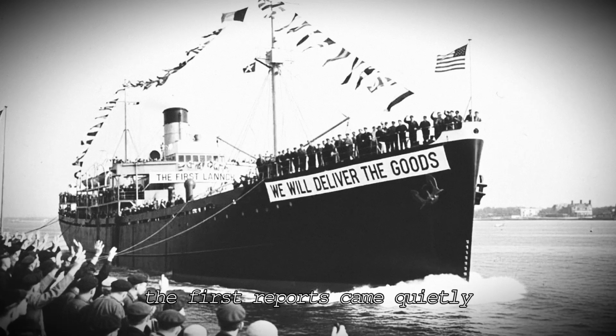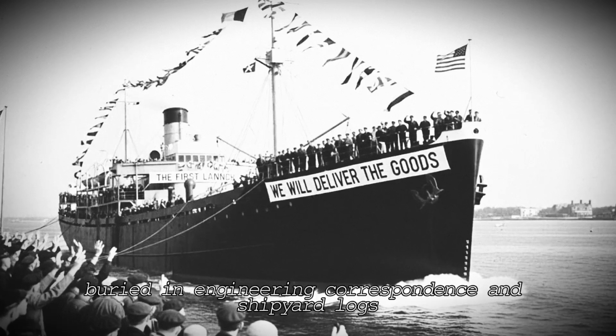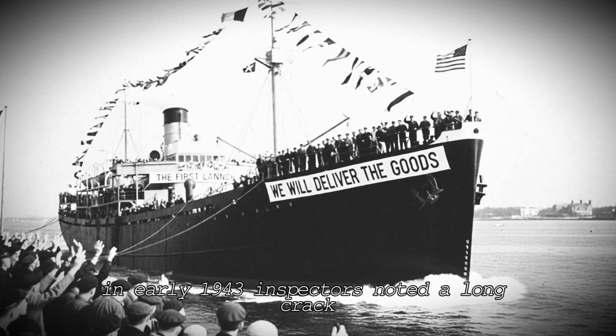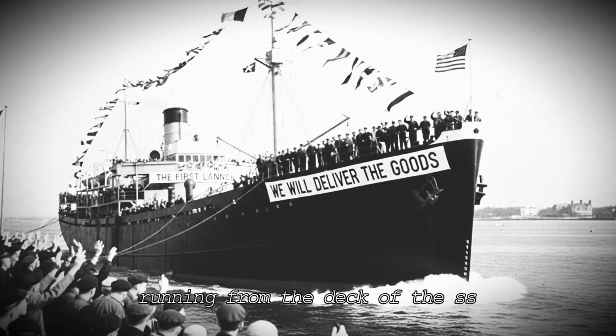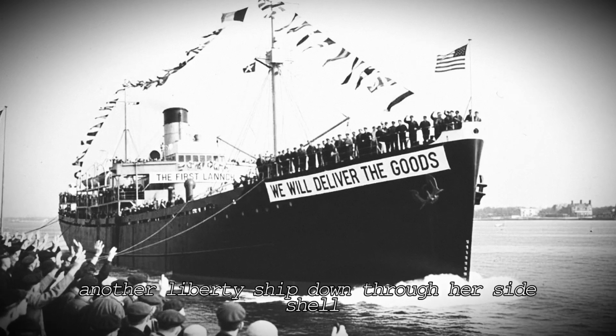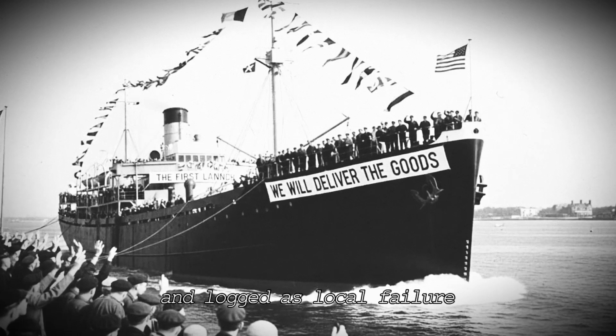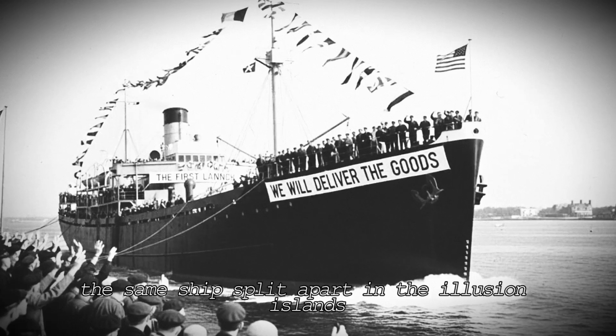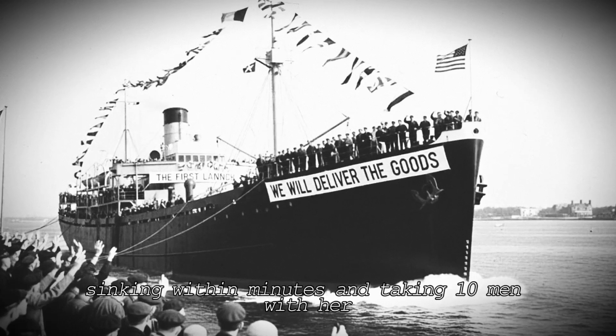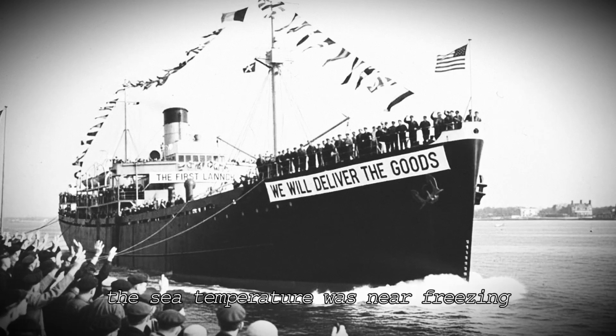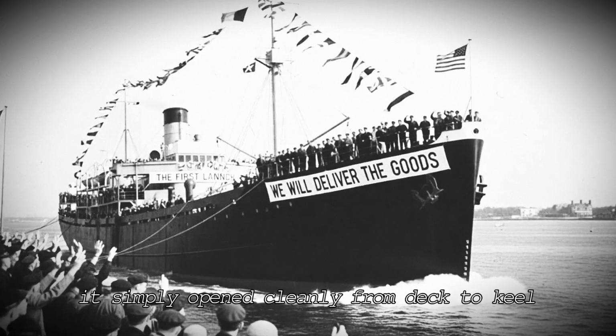The first reports came quietly, buried in engineering correspondence and shipyard logs. In early 1943, inspectors noted a long crack running from the deck of the SS John P. Gaines, another Liberty ship, down through her side shell. The fracture was welded over and logged as local failure. Weeks later, the same ship split apart in the Aleutian Islands, sinking within minutes and taking 10 men with her. The sea temperature was near freezing. Witnesses said the hull didn't buckle. It simply opened, cleanly, from deck to keel.